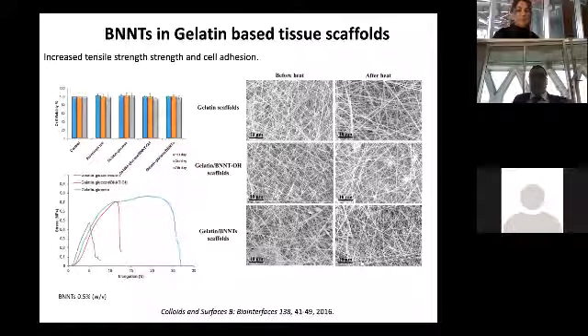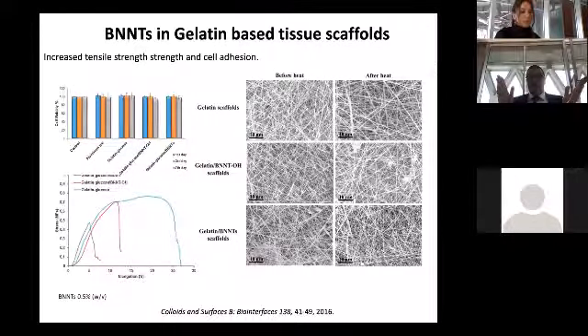And I know why these materials made these scaffolds better, because life does not like either hydrophobic or hydrophilic. It goes in the middle of the Gaussian curve. It likes both hydrophobic and hydrophilic. Because gelatin is mostly hydrophilic, when we introduce this hydrophobic material in very small amounts, if we disperse it very well, then the cells can adhere themselves to the scaffolds nicer, and they multiply faster.